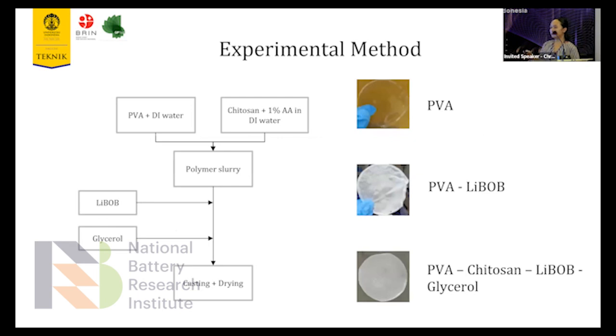Here we explain our experimental method where we dissolve PVA and chitosan in the deionized water and we turn it into a homogeneous slurry and we cast it on a petri dish and we dry it in a desiccator. At the right side, we can see that PVA alone results in transparent membrane. PVA with LiBOB salt results in opaque white membrane, but it is slightly inhomogeneous. But after we add chitosan and glycerol, it turns into more flexible membrane and more homogeneous.